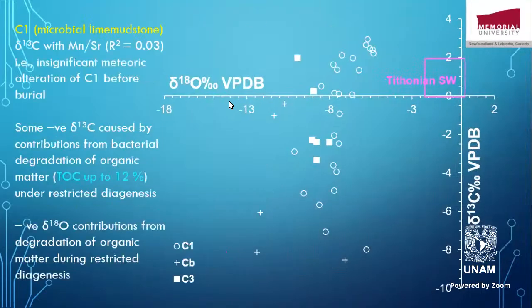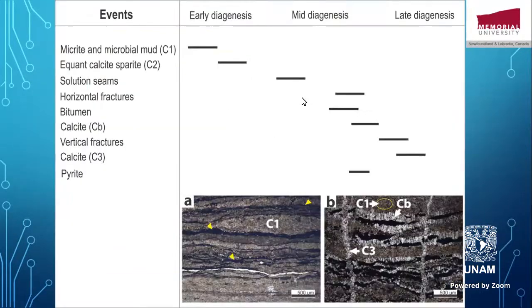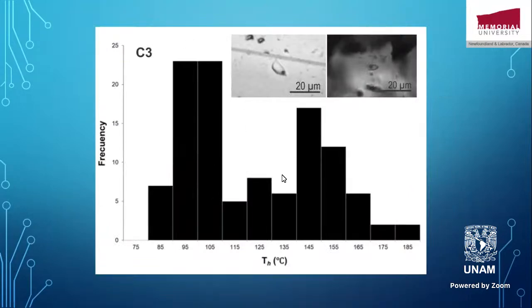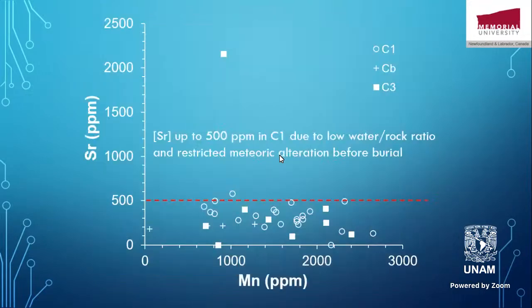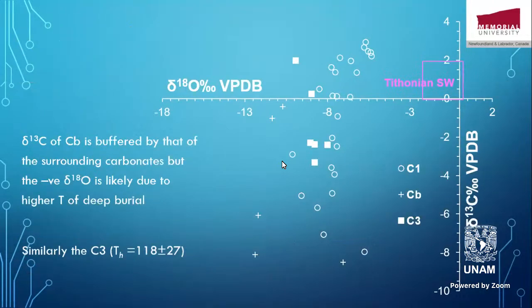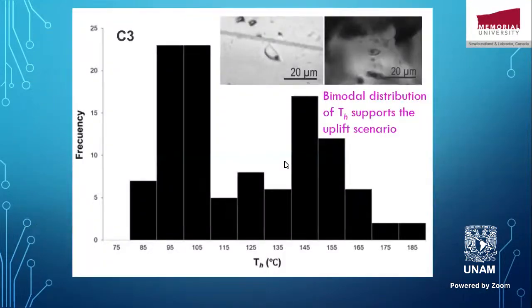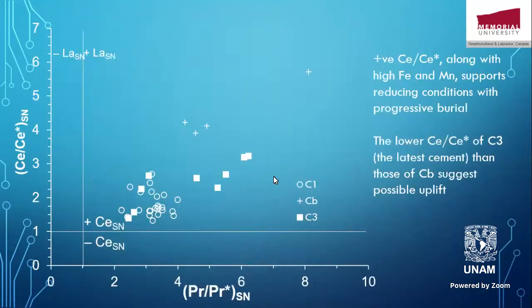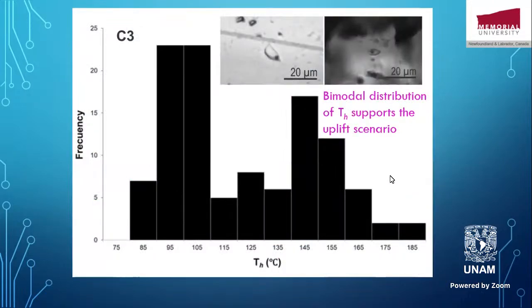And this is why we saw here, in that graph I showed you, two populations of homogenization temperature. One of them has higher temperature, the other one has lower temperature in the same latest cement C3, because part of the latest cement was formed at deep burial setting, and there was uplift after that, tectonic activity that caused the formation of the other set of homogenization temperatures during the precipitation of the C3. And of course, this is reflected also in the lower cerium anomaly of the C3, the latest cement, than that of the Cb cement, which suggests the possible uplift too. So this confirms the idea of the uplift.